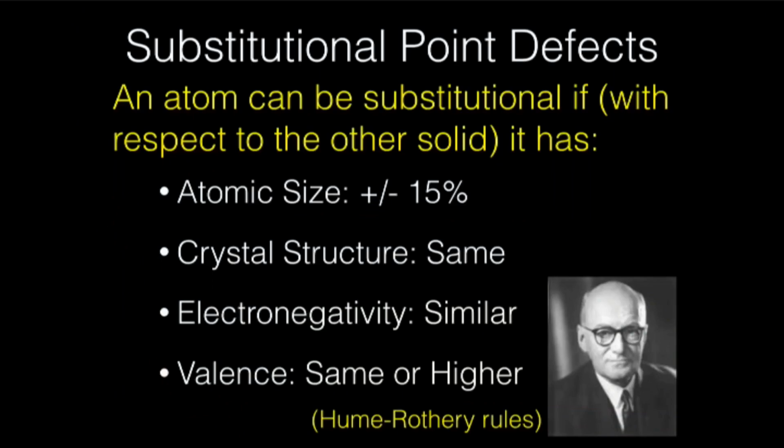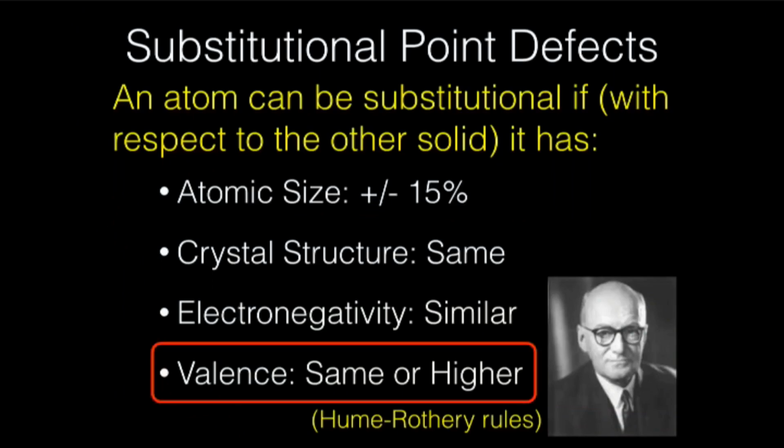But that got me thinking, and so I went and read some papers last night. Here's one on valency effects and relative stabilities. This is from the 80s, and I just wanted to cite something here. So here they say, almost a half century ago, so that's Hume-Rothery, the 30s pioneered the study of the effect of valency on metal alloy phase equilibria. They found that a lower valence metal like silver had only a very small solubility in a higher valence element like antimony, but that the solubility of the reverse was large. So that's where that rule came from.